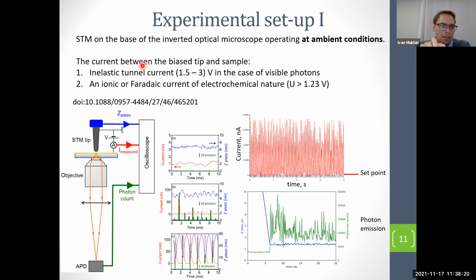It's well known that in air, all surfaces are covered with a very thin layer of water. It means that in the tunnel contact between the STM and the metal, there is a water meniscus covering the metal tip. If you'd like to achieve emission in the visible spectral range, you need to apply a voltage exceeding about 2 volts. It means that you have an ionic or Faraday current associated with dissociation of H2O water molecules. So in this system, at ambient conditions, you have two sources of current: tunnel current and ionic current, and unfortunately you can't distinguish them in experiment.